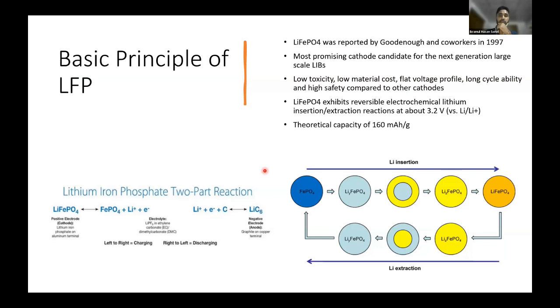Now we will talk about the basic principle of the LFP battery, how the LFP is actually working, that means how it behaves during charge and discharge. Lithium iron phosphate was reported in 1997 by Goodenough and his co-workers. And so far, this is the most promising cathode candidate, and it will be used largely in the coming years. As you have seen, it has very low toxicity, low material cost, flat voltage profile, that means it can hold the voltage for a longer time, long cycle life, and it has a very good voltage, which is 3.2 volt.